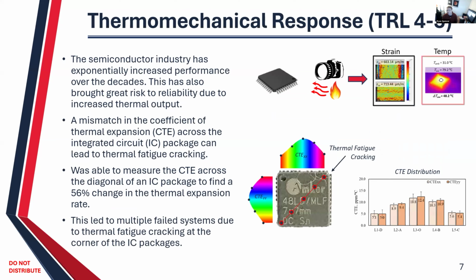Next one is thermomechanical response. We're actually supporting the semiconductor industry, where we are monitoring local CTE values, coefficient of thermal expansion, of this IC package, this microchip. This was a problem child microchip where it was always thermally fatigued, cracking in the corner. So we were able to actually measure and quantify this CTE mismatch that was occurring. We see a large distribution and mismatch in these values, and essentially confirmed why they were seeing this failure mode. And this helped support the R&D and development of this microchip for future production.